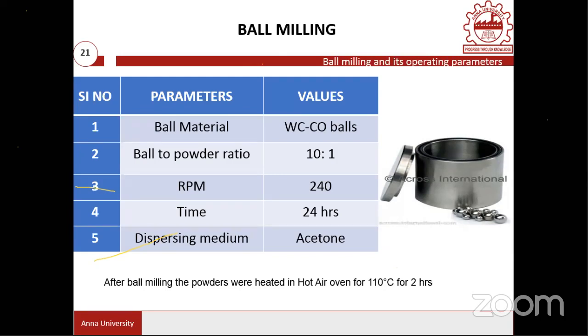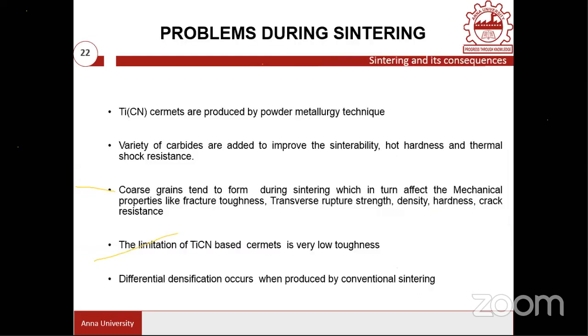Once the ball milling was over, we heated it. It's called annealing. To relieve the thermal stresses induced during the milling, we annealed this in a hot air oven for 2 hours at 110 degrees centigrade.